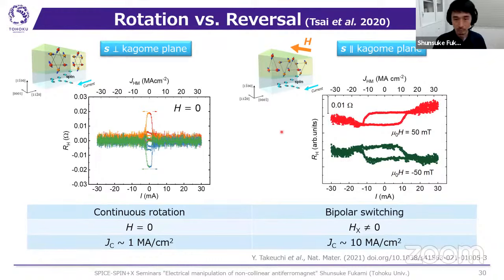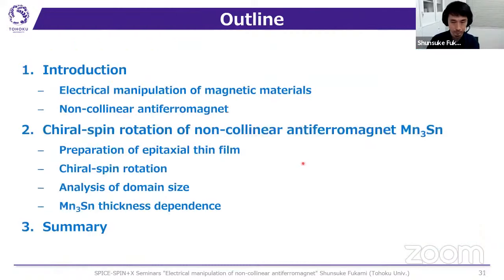And also one more important thing is that the critical current densities are largely different. So this behavior was observed at the current density of around 1 megaamps per square centimeter, but this phenomenon was observed at the current density of around 10 megaamps per square centimeter. Okay, so these are the differences between the chiral spin rotation and the chiral spin reversal.